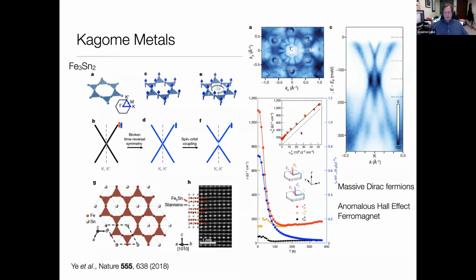One of the things that's quite interesting about these materials is that you see an anomalous Hall effect. Essentially, if you plot the Hall voltage, instead of having it go through 0 as you'd expect in a conventional material, there's a finite offset. That's an interesting type of behavior that people are trying to understand in these materials.